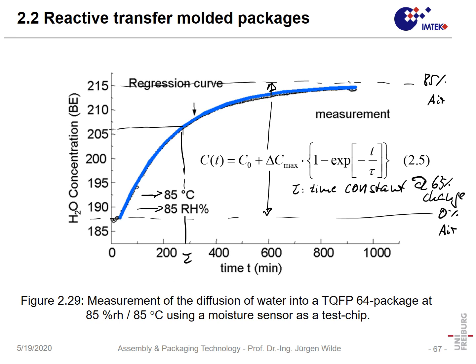And the time constant is, let's say, 260 or so minutes, so roughly 4 hours. That means after 4 hours, such a package is saturated in a moist atmosphere at 85 degrees centigrade. And that means it's a very fast process. As a rule of thumb, we can say with every 10 degrees centigrade which we lower the temperature, this time constant will double. So you could say maybe at 65 degrees centigrade we have 16 hours or so. So at room temperature it's not so bad, but it's still a matter of days until we have saturation of that package.